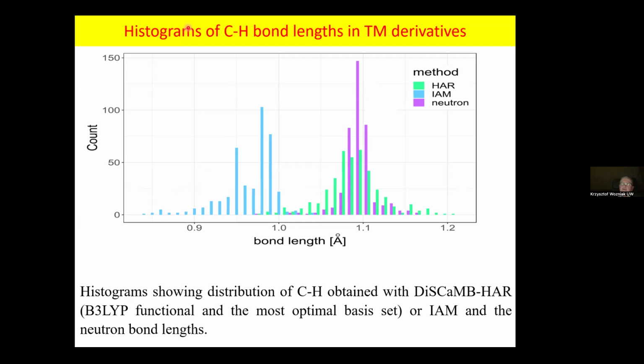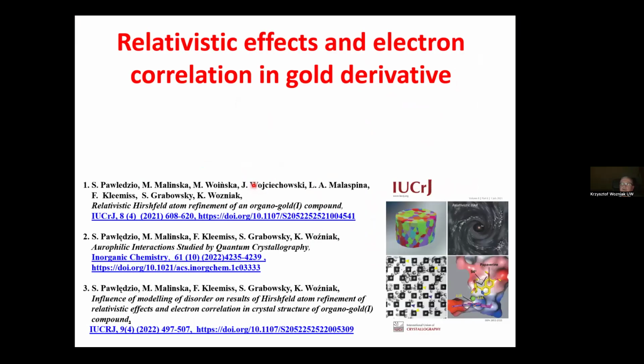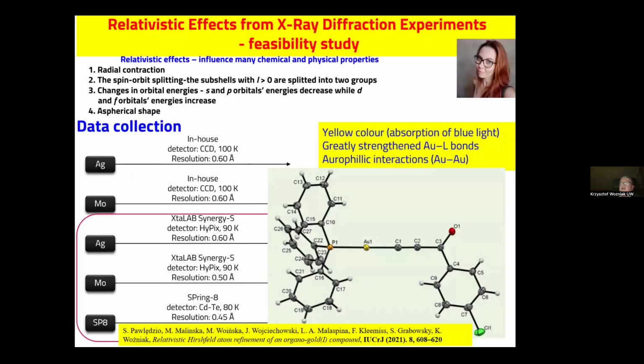And here is a distribution of CH bond lengths in transition metal derivatives. We've got from HAR this green distribution, from neutrons this violet one, and the blue one from the independent atom model. So clearly, quantum crystallography is giving proper distributions. In fact, because we can calculate this wave function at different levels of theory, at a certain moment we decided to verify whether we can attack really cool problems such as relativistic effects, and that was a part of the PhD thesis of Dr. Sylwia Pawlędzio, who is now at Oak Ridge National Laboratory.